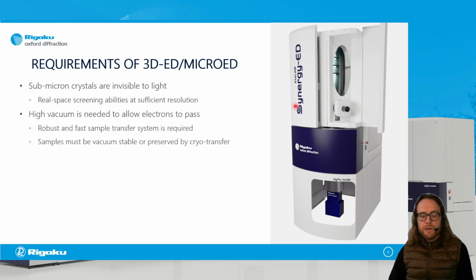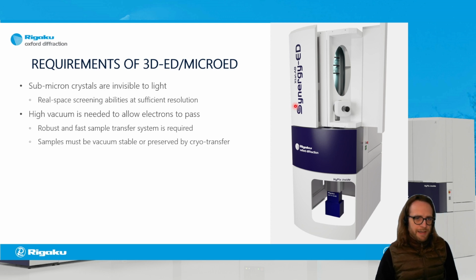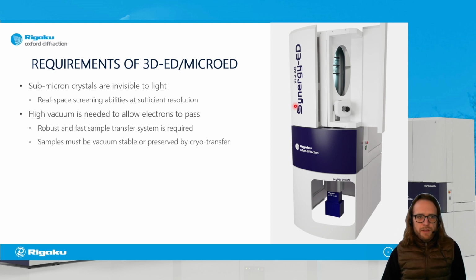Next, electrons, because of their strong interaction with anything, can only propagate in high vacuum, which means we need a robust and fast system to get samples into vacuum quickly, which also means that samples have to be vacuum stable or have to be preserved, for example, by freezing them outside the vacuum and then inserting them afterwards.